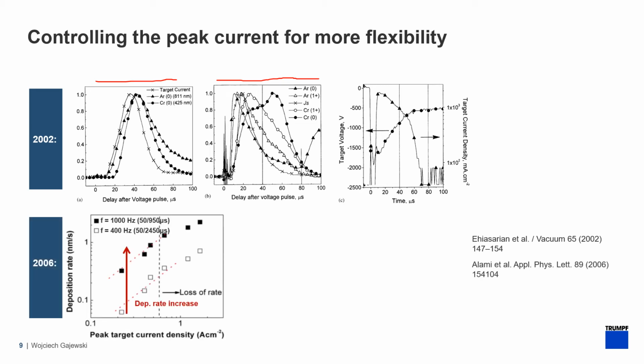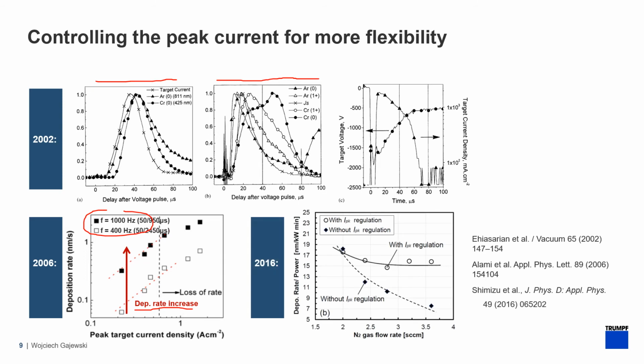Furthermore, it has also been discussed that control of the frequency of operation can influence, so to speak, the holy grail of HIPIMS operation, the deposition rate. And finally, the deposition rate can also be influenced if we are able to control the peak current of the HIPIMS, and then we can control the deposition rate not only in the metallic mode but also in the reactive mode.